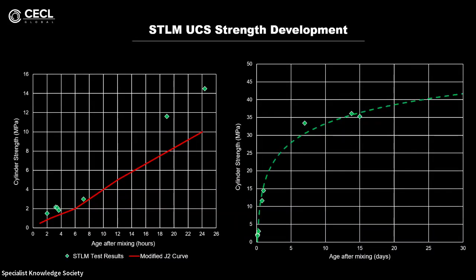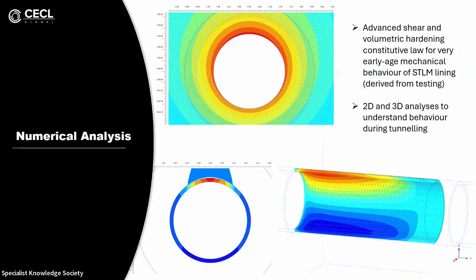If we look to longer term, so when we're expecting some hydration from the binder components, we achieve a good strength gain in the first 24 hours, so exceeding that required by the modified J2 strength curve, and structural concrete behavior in the longer term, where the chemical hardening of this ternary LC3 binder system has been working very well, even at high replacement levels. So we've done validation as well in numerical studies and finite element studies, 2D and 3D. So using the results of the physical testing in forming an advanced constitutive model for the STLM, running simulations at tunnel scale, and looking at strain-based considerations as well to understand its performance in the real world.